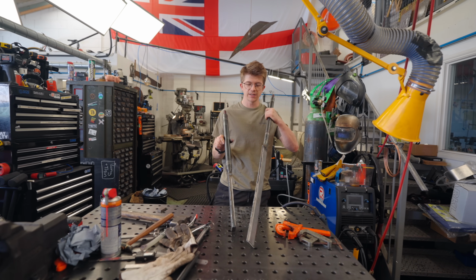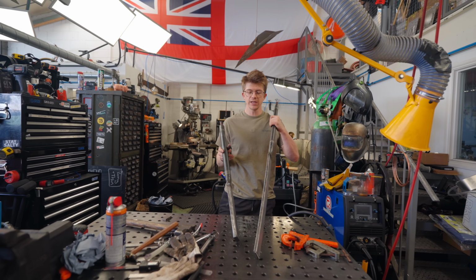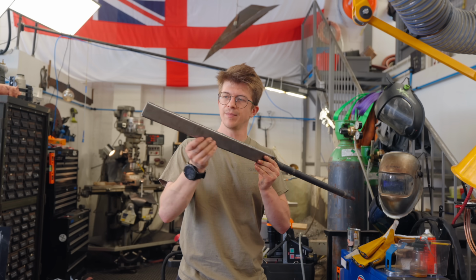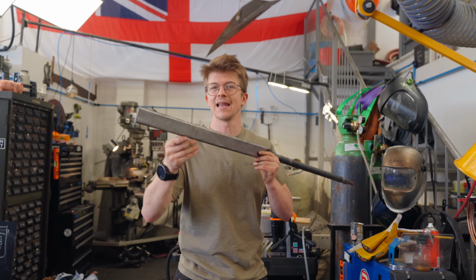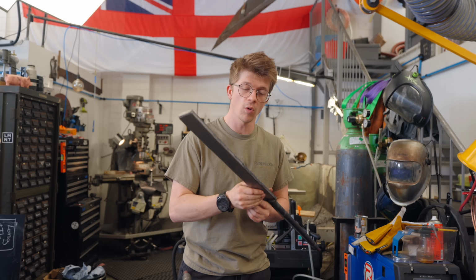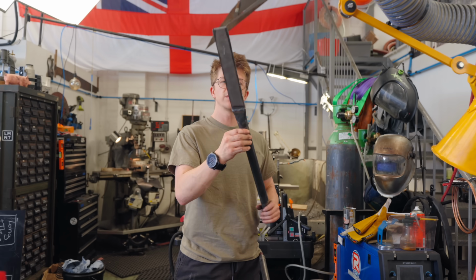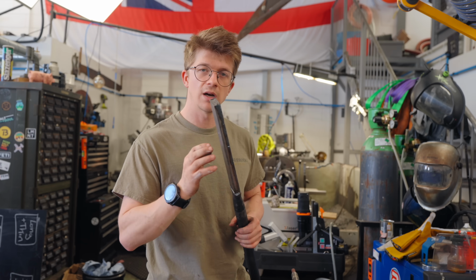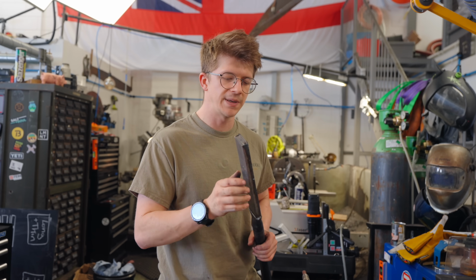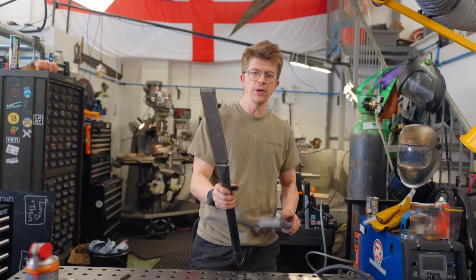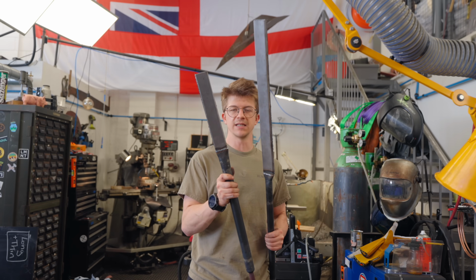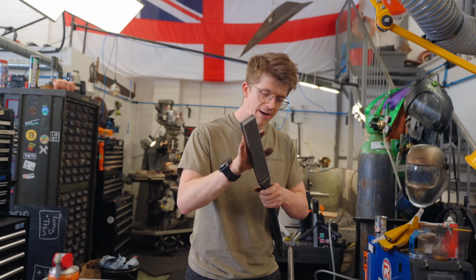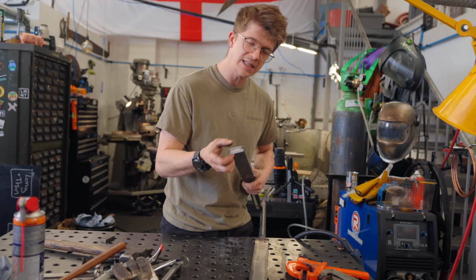We're trying to test if it's going to be better to bond these materials together in a thinner but longer profile where there is less drawing out and forging to do, or whether it's better for us to bond them together in a short and fat profile. I've used a thicker steel in our short and fat piece so that when we draw both of these out to about 900 millimeters, 6 millimeters thick, our short and fat piece is half the length and twice thickness,